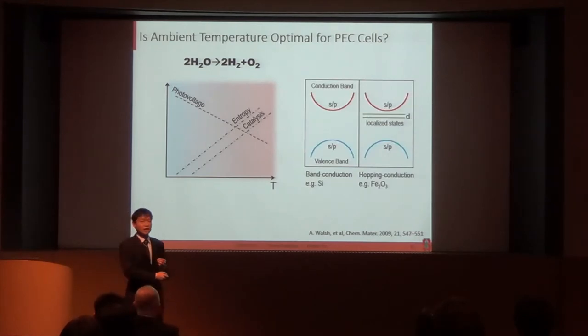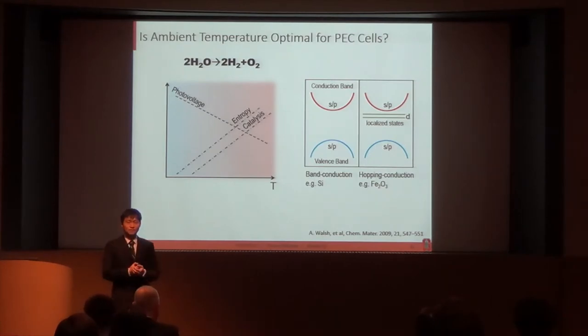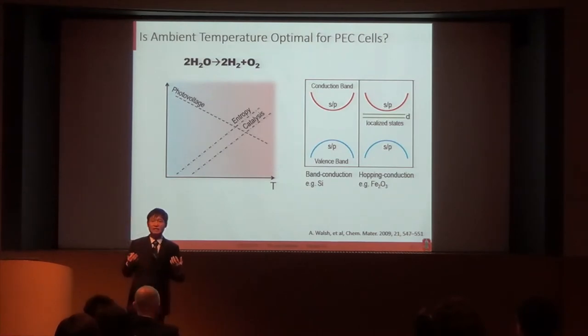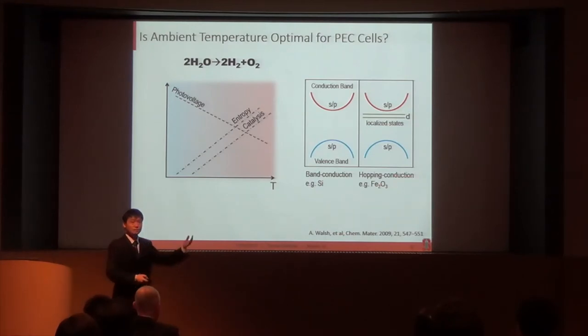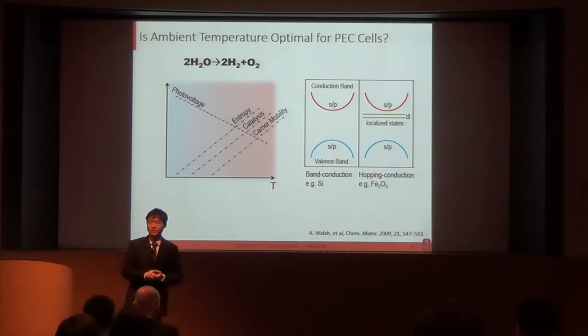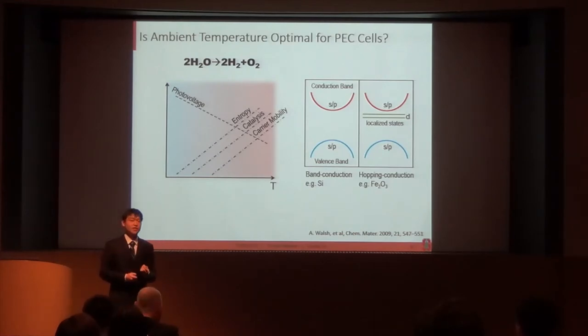This is because in semiconductors like silicon, the carriers conduct in a delocalized band, typically composed of s and p electrons. While in the transition metal oxides, there are localized states from the d band electrons. These localized states can trap the electrons or holes when they conduct. That makes for very slow carrier mobility. But this hopping conduction mechanism is strongly activated by temperature. So that's why the carrier mobility in transition metal oxides goes up with temperature. And that's something we need to consider as well.